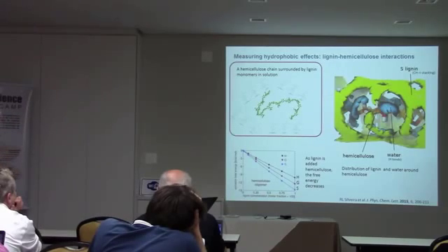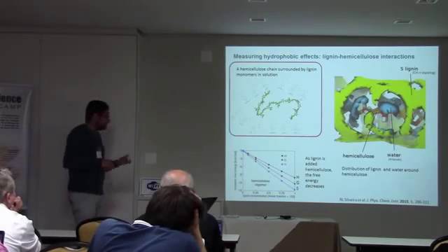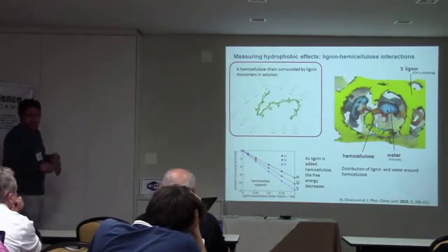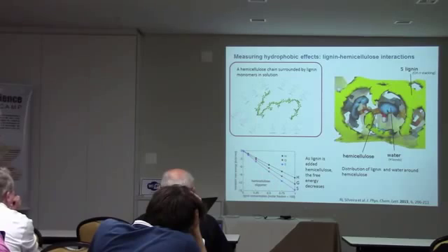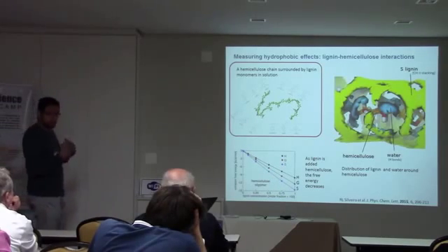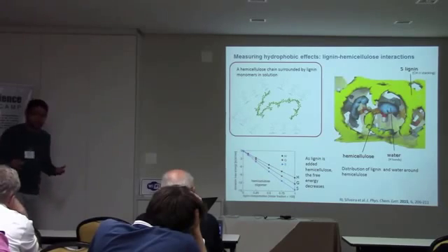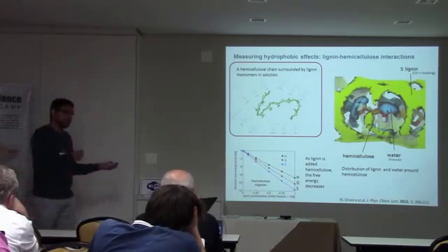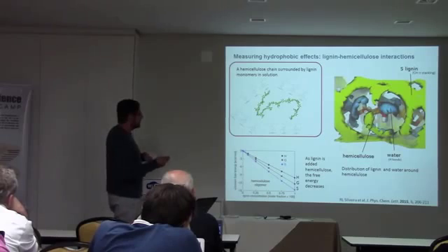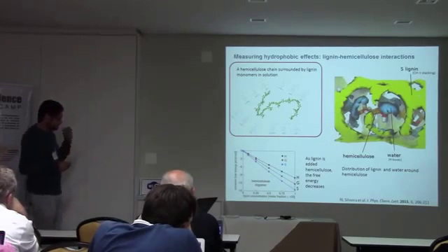And I also see that different lignins interact with different intensities with the hemicellulose. The S lignin, which bears more methoxy groups, interacts more strongly with the hemicellulose than the H lignin, which has no methoxy groups attached to the aromatic ring.